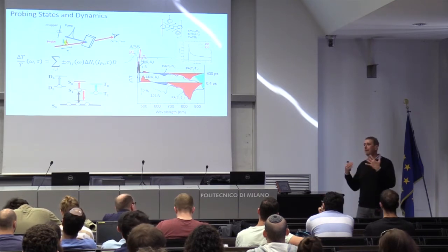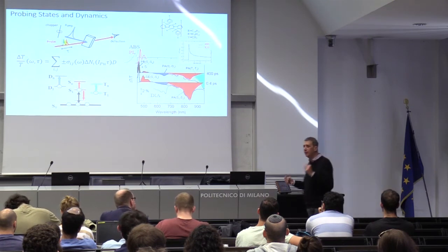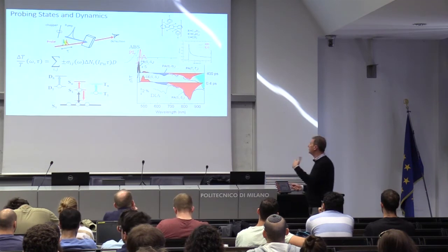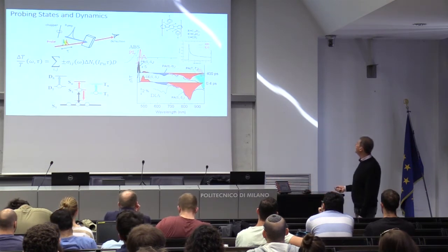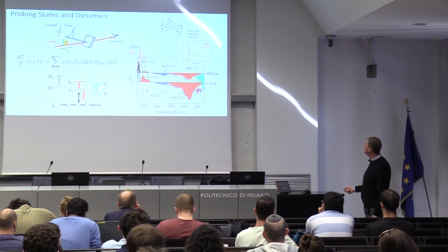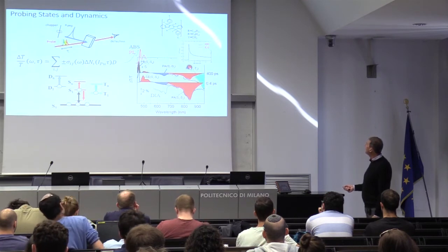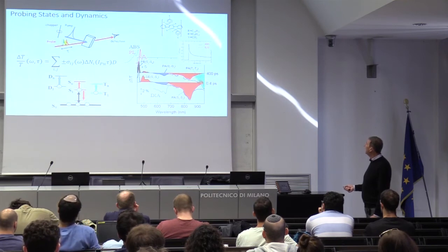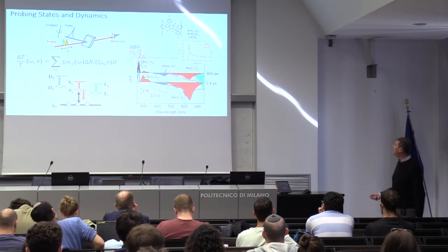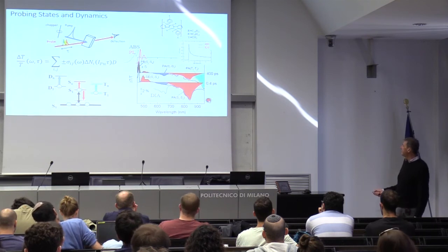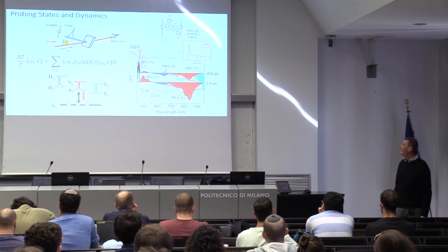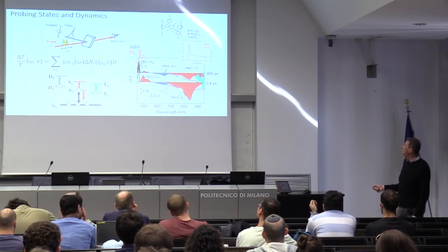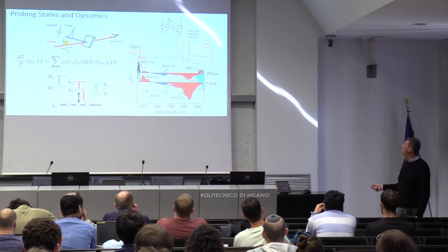So it means that some fraction of the excited state is forming charges. So we have singlet, neutral, charges, and then there is another peak here, which is interesting, that is there from the very beginning, but is obviously taking over. You see, it is the largest at 400 picoseconds. It is a long-lived state, which is appearing at, say, below 1 micron. That is exactly where, from other spectroscopy, you see the triplet is absorbing. So this is a triplet absorption.